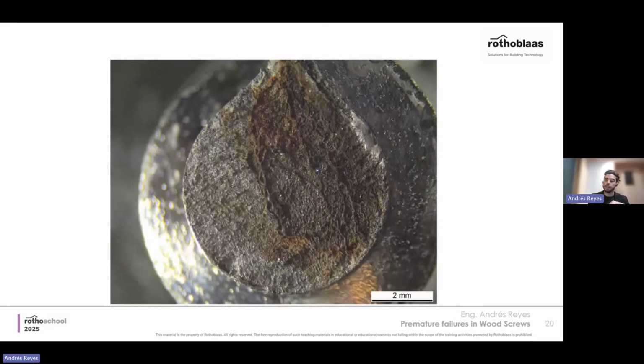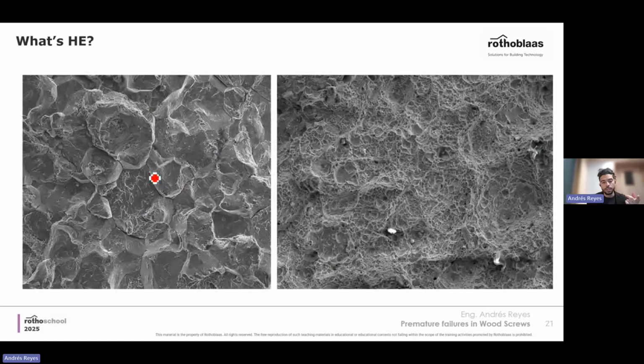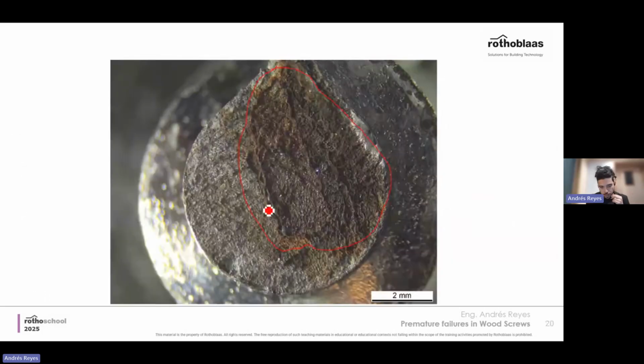So it's very perpendicular to the axis, very clear cut. You will see a different pattern. You see not the curves and not that much of an elongation like we saw before. And depending on the type of hydrogen embrittlement, you will see strong signs of corrosion as well. So that is a very strong symptom of hydrogen embrittlement. If you take a look a bit further, you will see as well the structure inside, if you take a look at the sections in some small pieces,